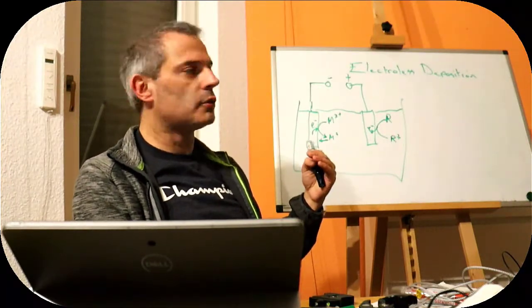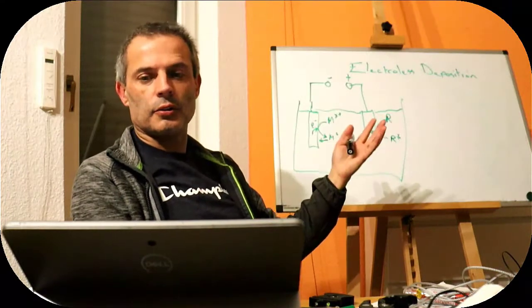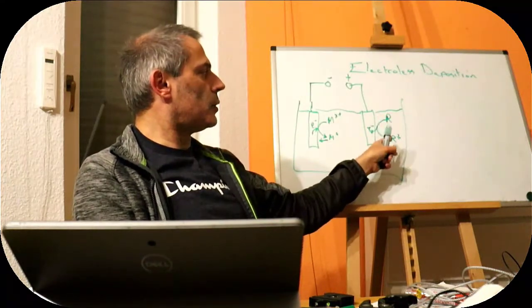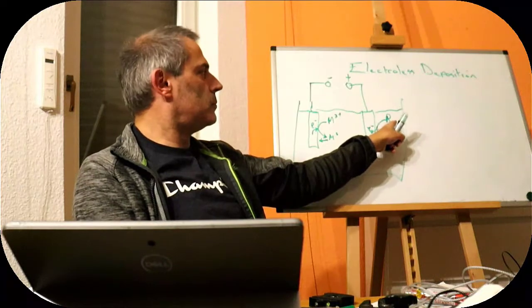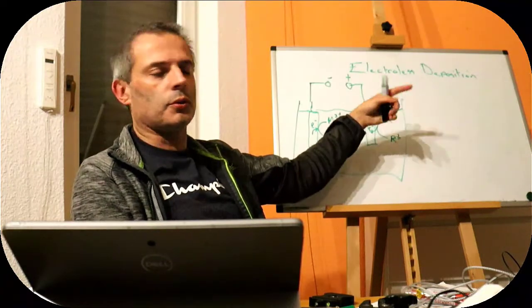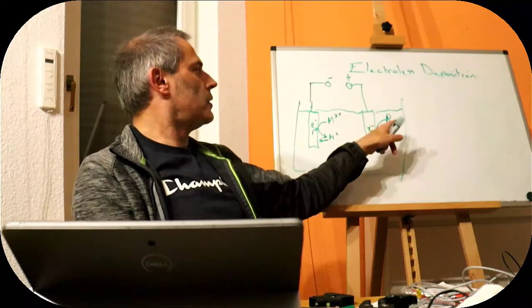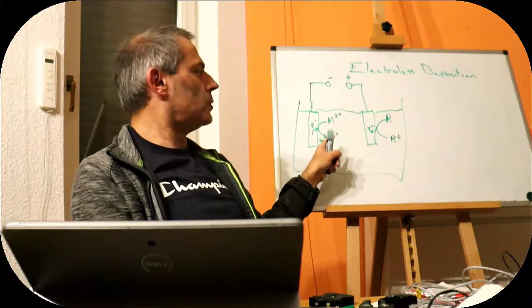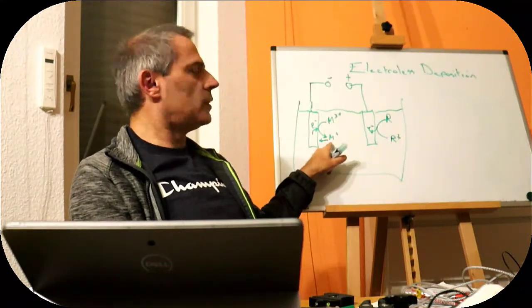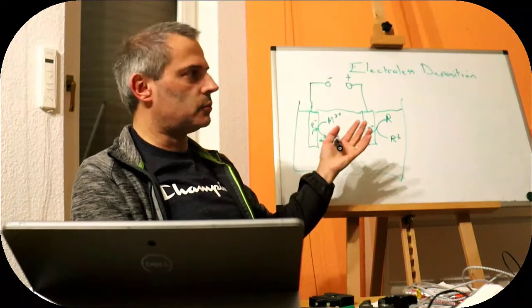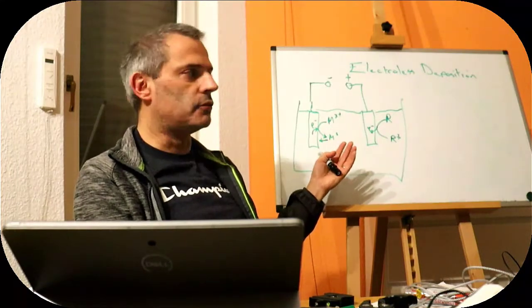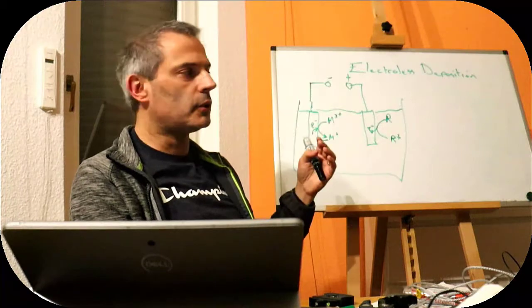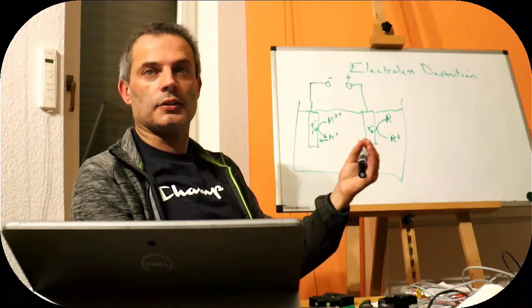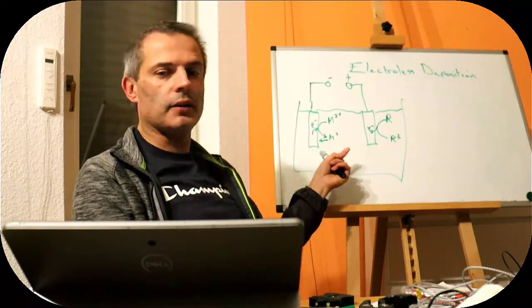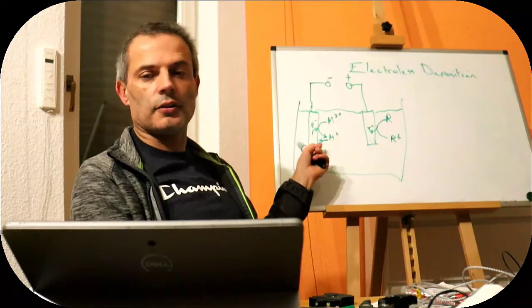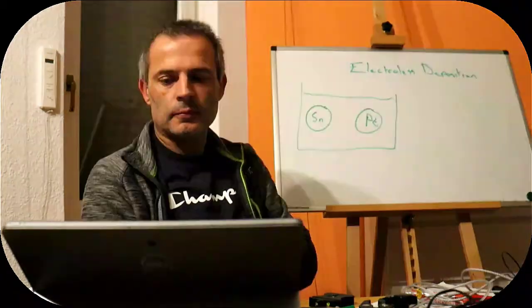If we want to do electroless deposition or electroless reaction, we need our reduced form, so the thing that's going to get oxidized, our reducing agent, to be more reducing than the metal ions. Otherwise we won't be able to cause the reaction to go forwards because we don't have a power supply. But we then get stuck with a problem. How do we make the metal that's formed stick to the thing that we want it to stick to?